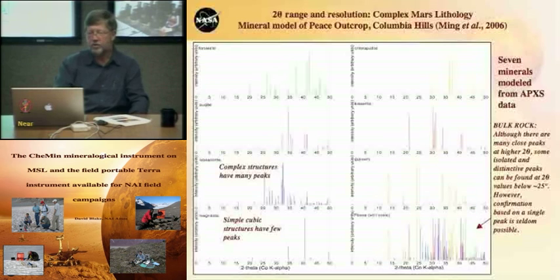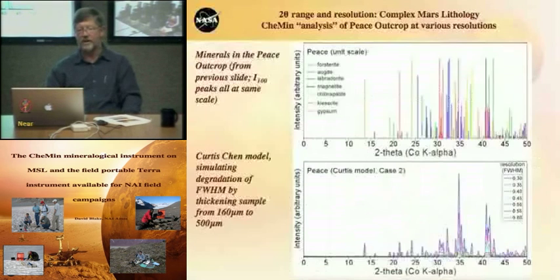And the main point we wanted to make with this is that if you look at the 2 theta range from about 5 out to about 50, you can get all the major peaks of interest for these phases. Okay, so let's go on to look at what kind of, we know the range of 2 theta we want.